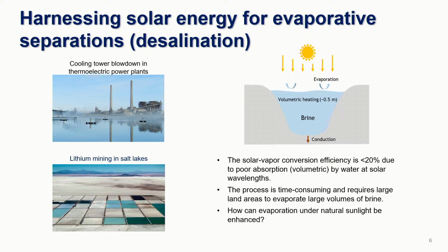So that is extremely low, and because of that, you either need very large land areas to do this kind of passive evaporation, and you also need significantly long times. So for example, for lithium mining in ponds that are about a meter deep, they have to leave those salt solutions in there for 6 months to a year in order to get all of that water to evaporate. So the question is, how can we really just enhance evaporation under natural sunlight?